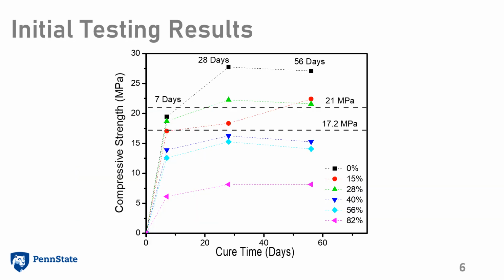This graph shows the compressive strength test data as a function of cure time for the various percentages of plastic incorporated into the concrete. Also on this graph, you can see a 17.2 megapascal minimum requirement and a 21 megapascal recommended requirement. After a full 56-day cure time, up to 28% loading level of plastic achieved the 21 megapascal requirement.